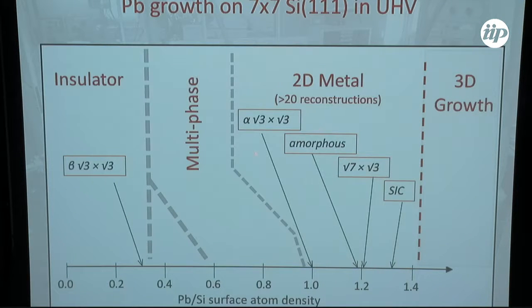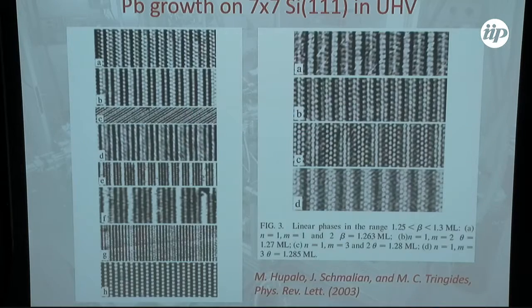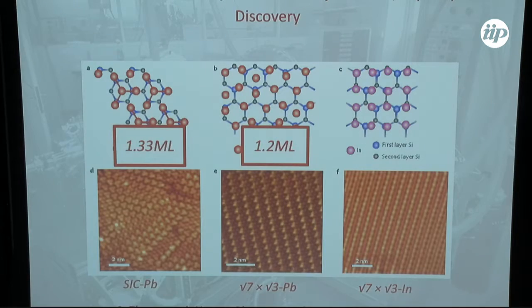We know that this amorphous monolayer is not superconducting. However, there are more dense structures, square root 7 by square root 3, and the so-called striped incommensurate structure. One square root 7 by square root 3 corresponds to 1.2 monolayers of lead per monolayer of silicon. It means that we have more atoms of lead than atoms of silicon on the same surface. Okay, so it's a very dense structure. Here, the interatomic distance of lead is shorter than in bulk lead, so it's a sort of pressure. Okay.